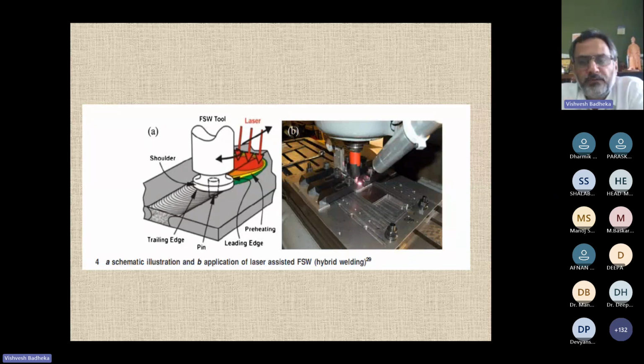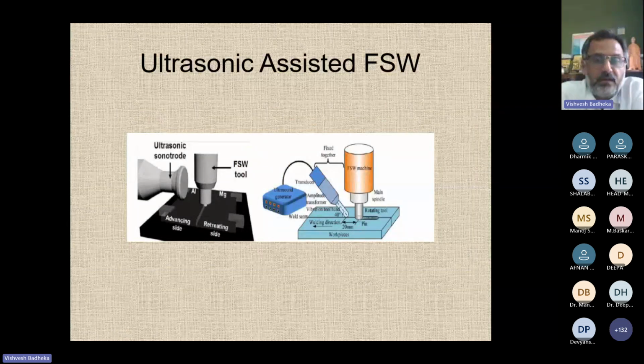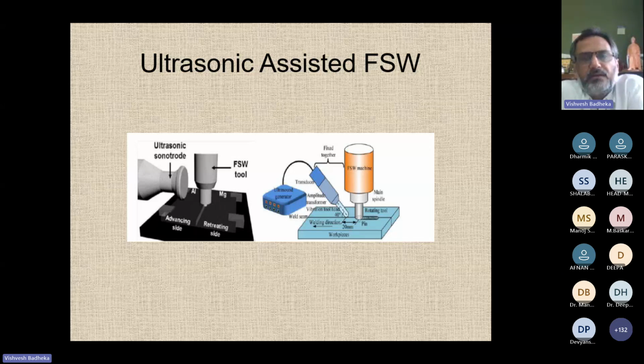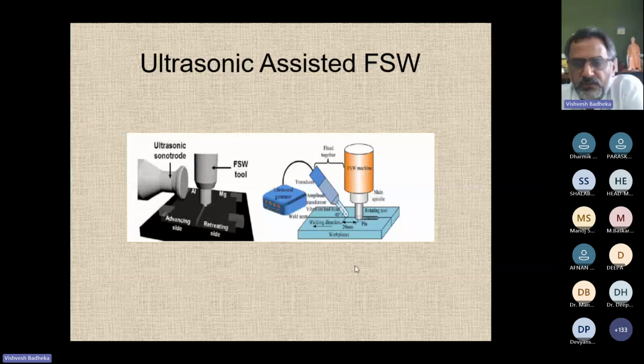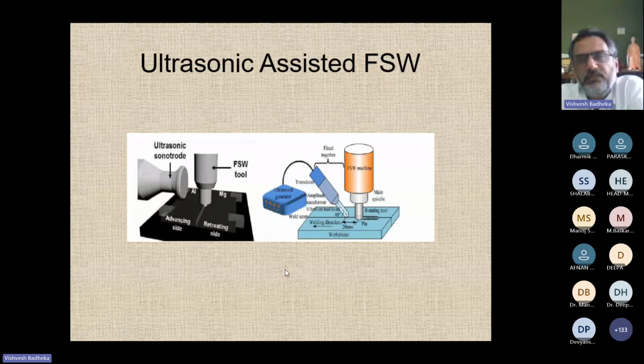So in order to reduce that stringent requirement of the tool material and the wear of the tool, the load on the tool, there is an additional variant which has been worked out, which is called assisted friction stir welding, wherein the heating can be done before the tool reaches. You can supply some extra heat, as you can see in the diagram, with the help of laser, gas tungsten arc welding, plasma, or oxy-fuel flame also. You can see one more picture wherein you have ultrasonic assisted FSW, wherein you are supplying extra ultrasound, so that you can have a better stirring and mixing of the material at the interface. You can generate a good quality joint.